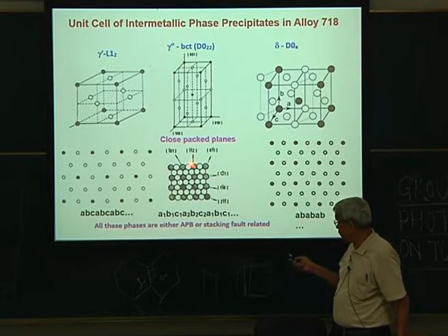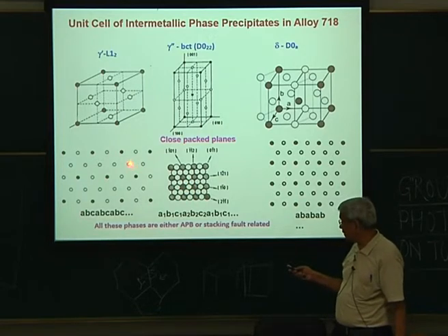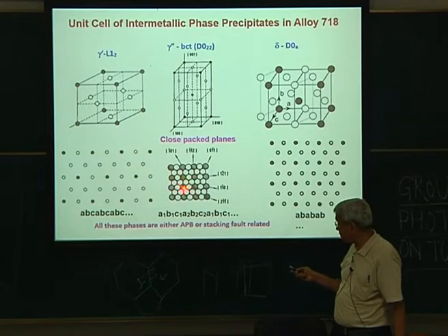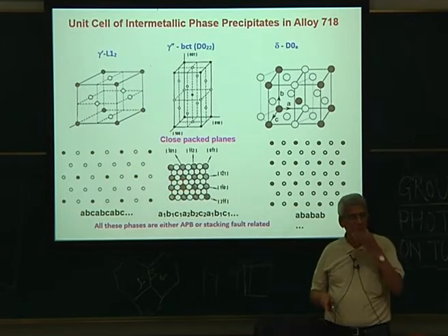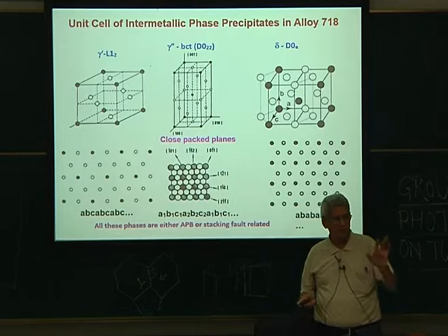This structure, if we look at the closed packed plane, it's again also like an FCC structure. Only thing is that now the atoms which are minority atoms which are occupying the positions on the plane, they are slightly different. Right? Here, if you see, you have a threefold symmetry still present along 111. Here, if you see, the threefold symmetry is lost. Okay.